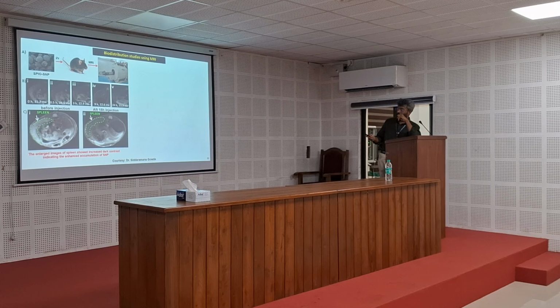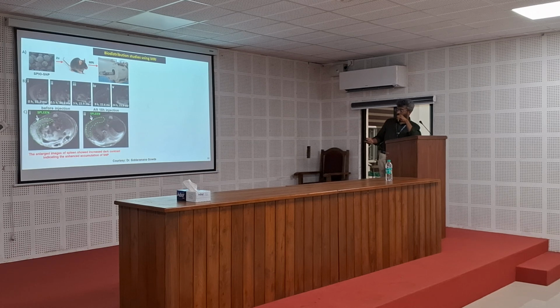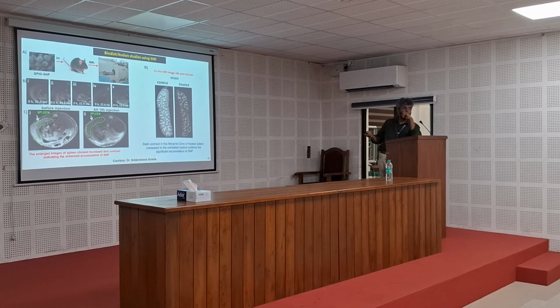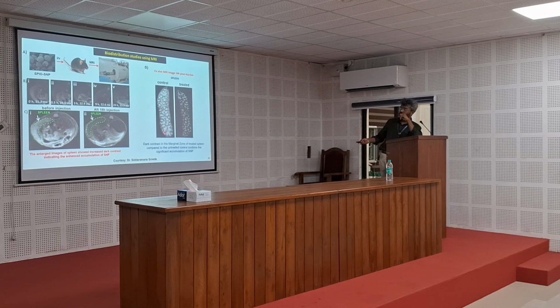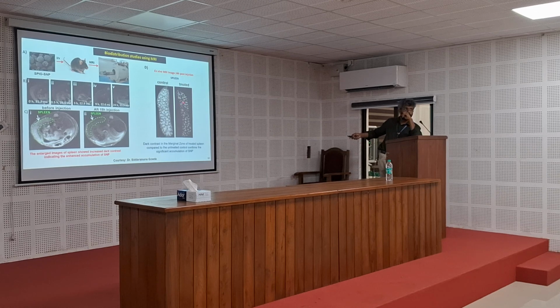So that is the MRI data. Now after 24 hours, we euthanized the mouse and took out the spleen. This is how the spleen looks. See the architecture. This is before injection, the untreated control spleen, and this is the treated one. You see that this area is getting darkened, and this darkening is mainly in the white pulp region of the spleen.